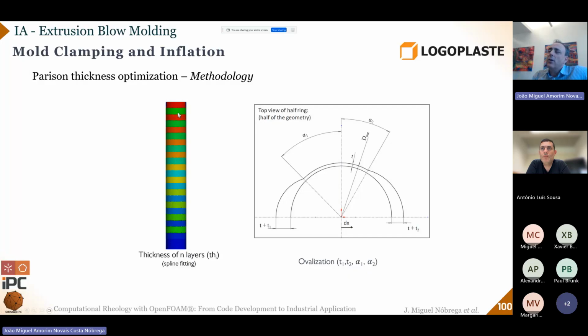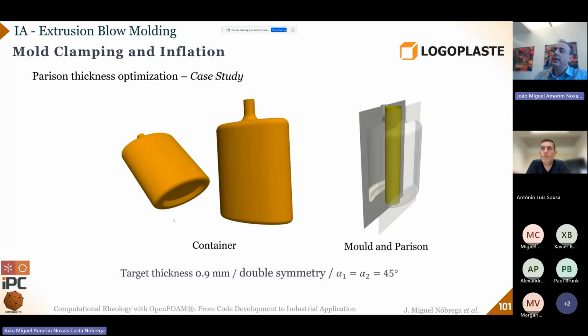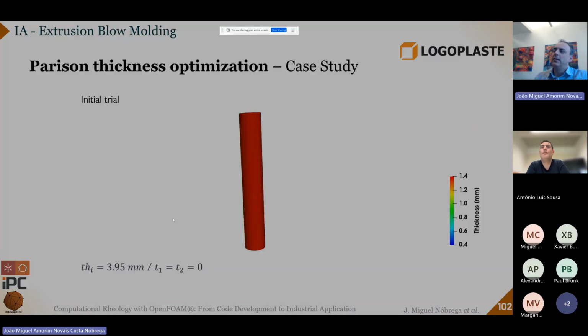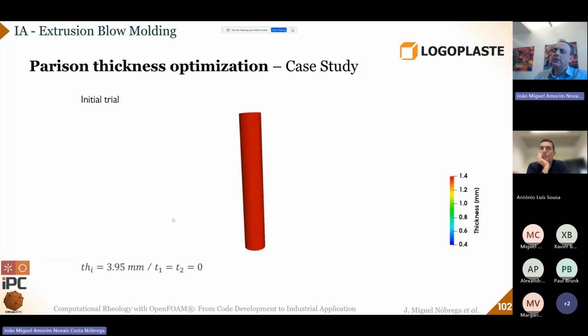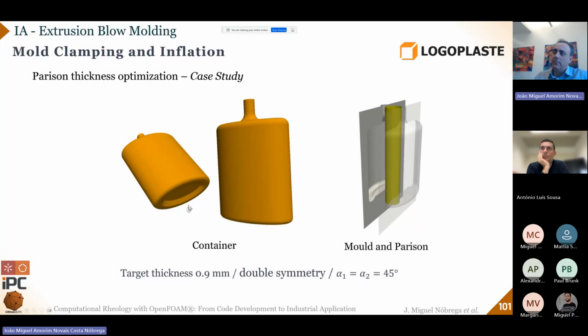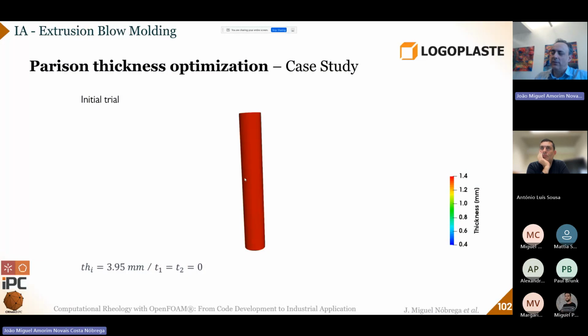The issue is, which should be the appropriate thickness of each of these layers in order to get the final thickness distribution we want. In order to do it, we did the same. So we model, we do optimization, and this is one example. Again, I will not cover it in detail. The example is an ovalized container that is not easy to manufacture experimentally.